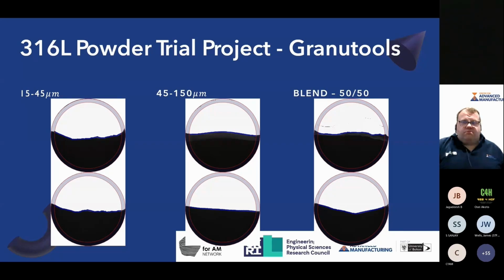What the GranuDrum looks like, so the top image in all three cases is the after initial settle. You load the powder, the machine will then do an initial calibration and create its horizontal level before it then starts to rotate. At the end of its rotation up to 10 RPM and then back down to 2, it will then go back to this horizontal position. What we can see is an idea of whether the powder's sitting as you'd expect. So again, the large powder mounded in the center, and then at the end, relatively flat. The 15 to 45 shows there certainly is some cohesivity. There's something causing some kind of clumping, and then the 50-50 blend is in between the two. Again, it's an informative data point in what we'd expect to see with powders.